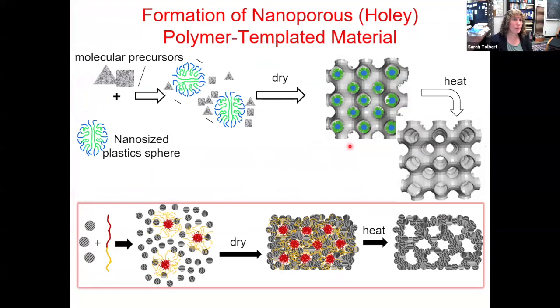Okay, so we use chemistry to make these materials, and we use what is called polymer templating. So we make little nano-sized spheres of plastic, and we make them using self-assembly of block copolymers, or we make what I call plastic mayonnaise. So we do an emulsion polymerization of polymers like standard polymethyl methacrylate to make tiny spheres. And then we co-assemble either molecular precursors or preformed nanocrystals with our plastic spheres to make inorganic-organic composites that have our battery material surrounding our plastic. And then we simply burn up the plastic to carbon dioxide and water to leave behind our pores. So it is a very easy way to convert any material into a porous material.